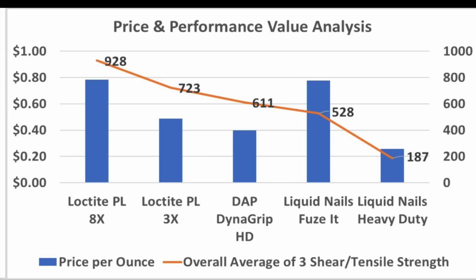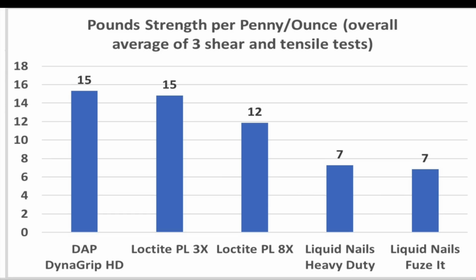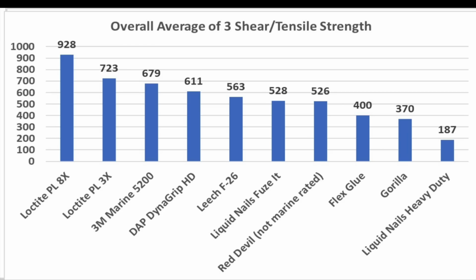Liquid Nails Fuze It cost approximately the same per ounce as 8X, but demonstrated less strength on average than 8X, 3X, and DAP Dynagrip. Another way to look at value is pound strength per penny. DAP and PL3X delivered approximately 15 pounds of strength per penny compared to 12 for PL8X and 7 for the Liquid Nails products. If you saw the previous video on marine construction adhesives, you might be wondering how they compare to those not rated for continuous water exposure.